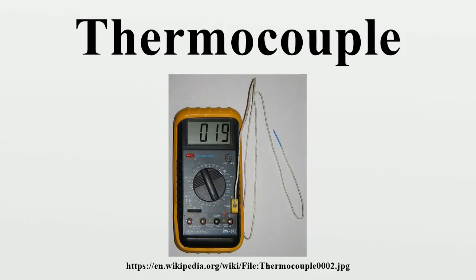Aged sections may see exposure to increased temperature gradients from hot to cold as the aged section now passes through the cooler refractory area, contributing significant error to the measurement. Likewise, an aged thermocouple that is pushed deeper into the furnace might sometimes provide a more accurate reading if being pushed further into the furnace causes the temperature gradient to occur only in a fresh section.